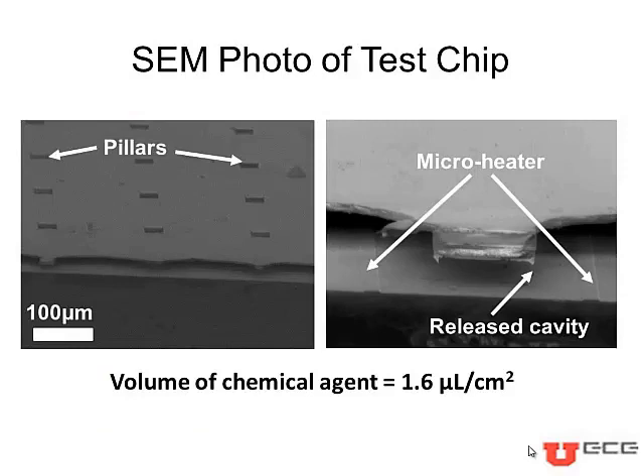These photos show the cross-section of the reservoir. In the picture on the left, we can see the support pillars which prevent the top wall of the reservoir from collapsing. While in the picture on the right, we can see the micro heaters embedded in the bottom wall of the released cavity. The volume of the chemical agent that the reservoirs can contain is approximately 1.6 microliter per centimeter square.